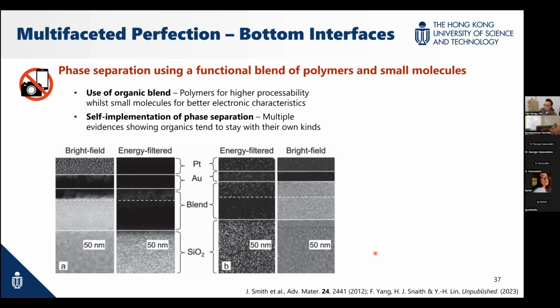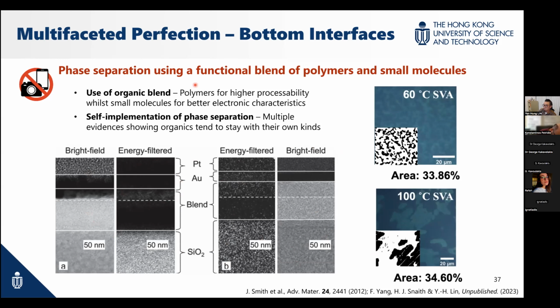So we took some inspiration from Thomas's organic field effect transistor, and tried to use organic blends. Organic blends will have this kind of separation between polymer and small molecule. So when we blend them together, the small molecule and polymer separate during the deposition process. We implemented this approach to make our transporting layer at the bottom interface for a perovskite solar cell. We use different approaches to form these organic blends, and different conditions have different distributions of small molecule and polymer.